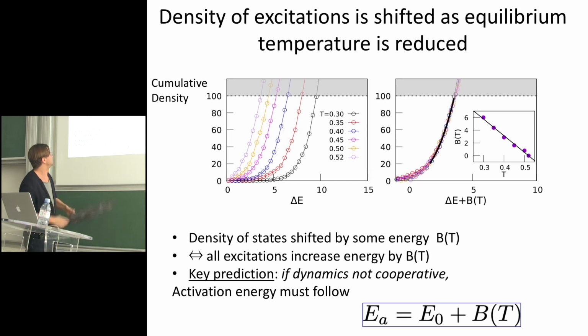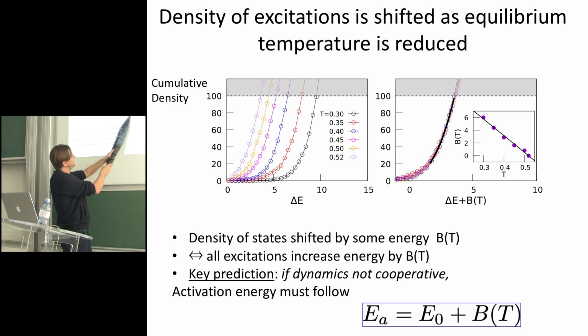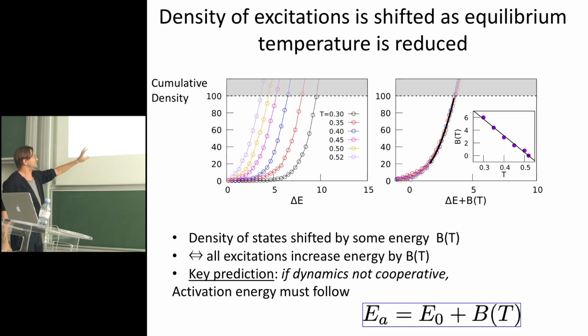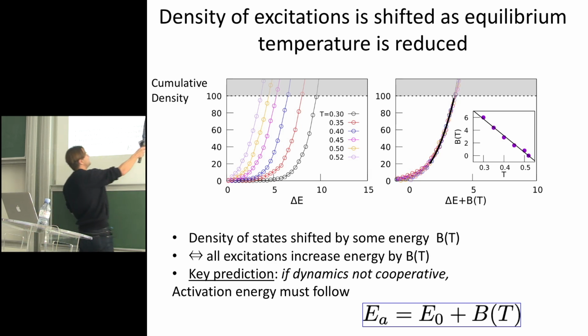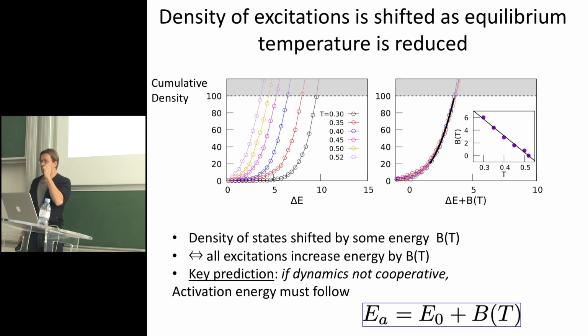Really, the key finding is that those curves are essentially collapsed just by a shift. Here I just took those curves and added a constant, and they all look alike. And that's a key observation. This shift means it's equivalent to having all the excitations in your system increase their energy by some quantity B of T that we can extract by collapsing those curves.